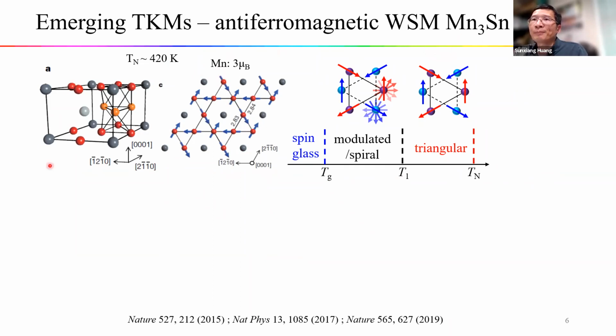Let's start with the Manganese-tin. It is an antiferromagnet with a Néel temperature of about 420 Kelvin. Each manganese carries a moment of about 3 μB. They have a very rich non-collinear spin texture. Roughly between the Néel temperature and some transition temperature T1, we have the so-called inverted triangular spin texture. Below T1, we have a modulated, spin helical state. In some cases, there could be another transition below this, the spin glass state. The T1 and the TG depend sensitively on the composition and the fabrication process.